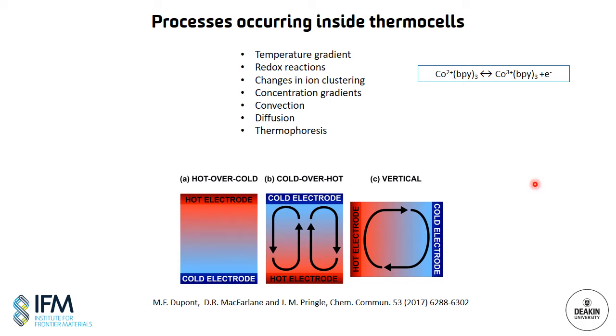The species will also undergo diffusion, and thermophoresis can also occur, which is where the thermal gradient itself can lead to concentration gradients, with the larger species clustering on the cold side of the device. And it's important to know that all of these factors will be interdependent in complex ways. And they'll also be sensitive to the cell size, the geometry, and the orientation. And if the temperature gradient is changing as a function of time, or the load resistance is, then these factors will also be time dependent as well. So although the design and the way the devices work is relatively simple, there are potentially really complex things that can occur inside them, and this is something that we could look at potentially using magnetic resonance imaging.